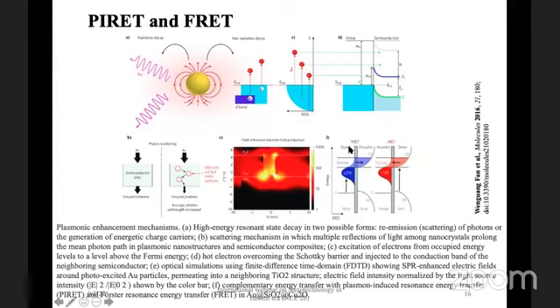So the idea is to use these two phenomena to look into the zinc sulfide nanowires which we have grown and use gold over there, and to see if we can quench certain photoluminescence in the semiconductors or not. The center one is an image in which the bright spots show actually the plasmon field, and you can see these ones are the TiO2 slabs which are on the right side, and you can see these bright spots extended into the semiconductor material.